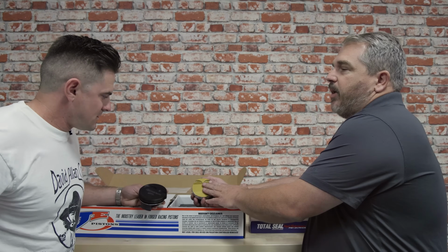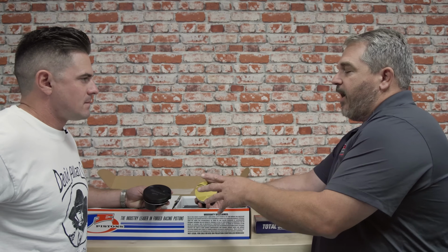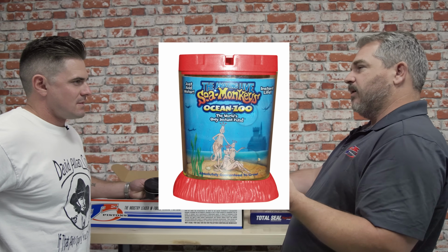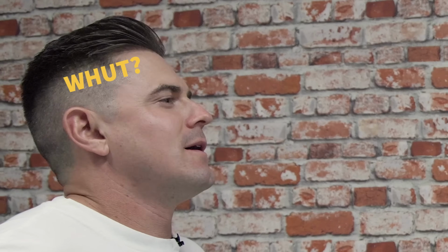So the difference between the two is this is a sprayed on coating, right? Where anodizing actually grows off the part. So it's adhered to the part differently. The easiest way to explain it is it's basically like sea monkeys that grow off the aluminum. So it's etching the part and creating that protection layer. What's nice about it is people talk about coatings either flaking off or burning off. That will never happen with an anodized part.